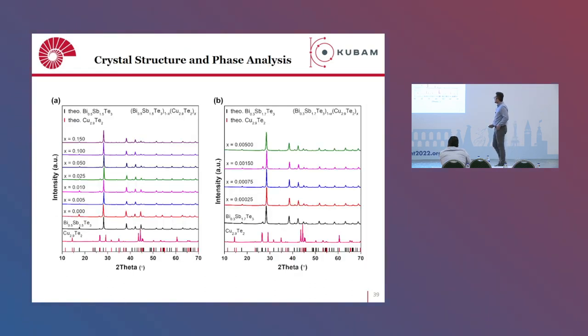And these are the X-ray diagrams. Here, this is the theoretical pattern for copper telluride, and this is the bismuth antimony telluride. The black ones are the bismuth antimony telluride. The red one is copper telluride. So it is almost single-phase bismuth antimony telluride, with no detectable copper telluride, because the amount of doping here is quite low. This is x from 0 all the way up to 0.15. A small amount of doping. Similarly, this is BST5, which is bismuth 0.5. And this is BST3.